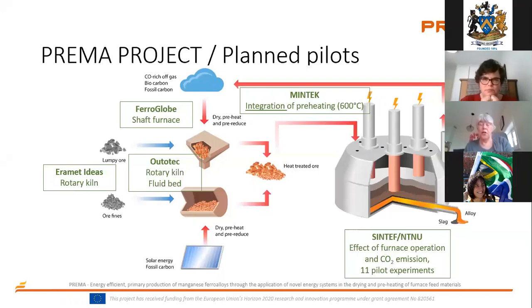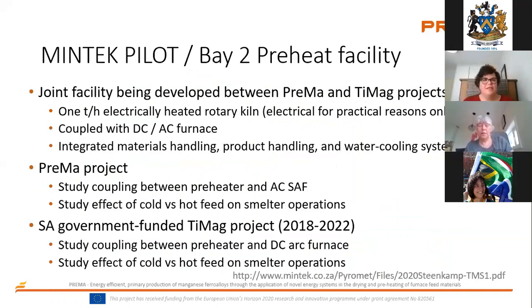But the important thing that we will not be able to investigate by this method is a really important challenge: the feeding of warm material from the pretreatment unit to the submerged arc furnace. That is critical to get the energy and CO2 advantages we want. This will be done in a large-scale pilot at Mintek, where they will run for several weeks, combining the pretreatment unit, the feeding, and the submerged arc furnace. The results from this will be combined with all the other pilot experiments to give us information about the effect of preheating on pretreatment with the different technologies. I think it is very crucial that we are able to have this large-scale pilot and to also do the feeding of the raw material. And Joalet will tell you more about that. So, Joalet.